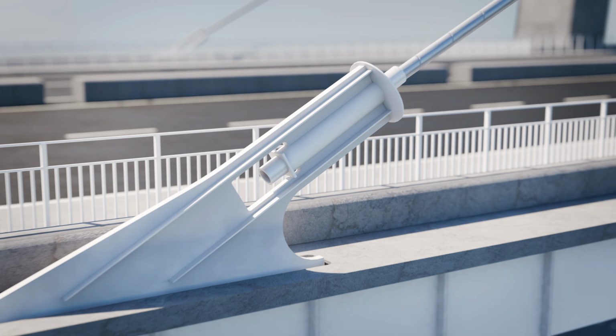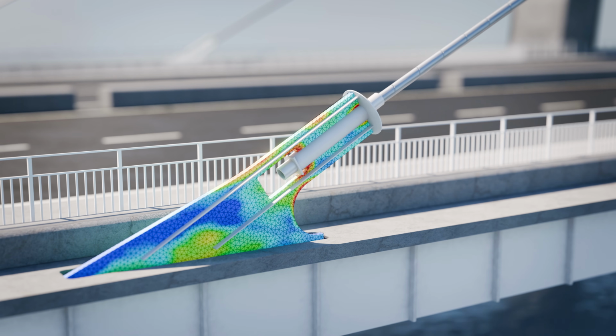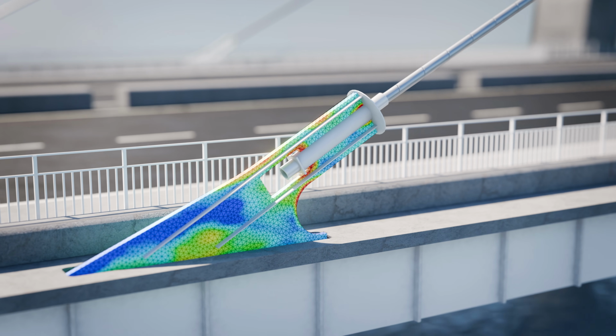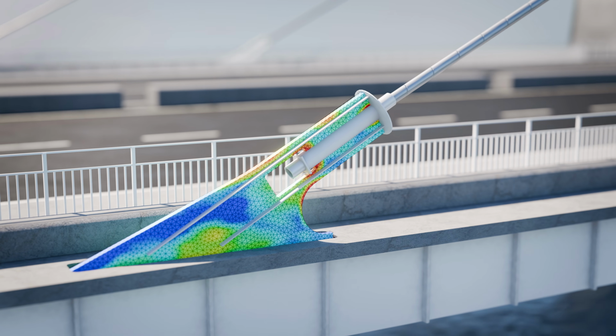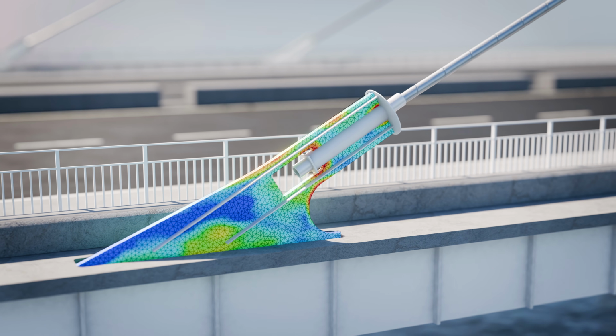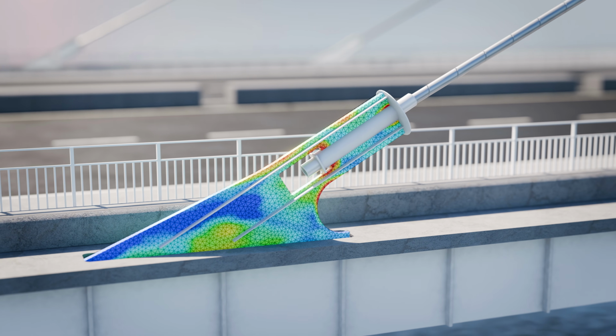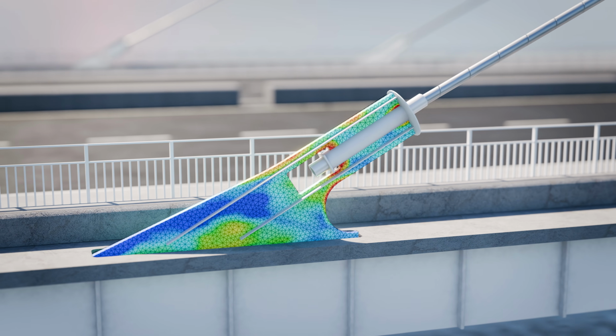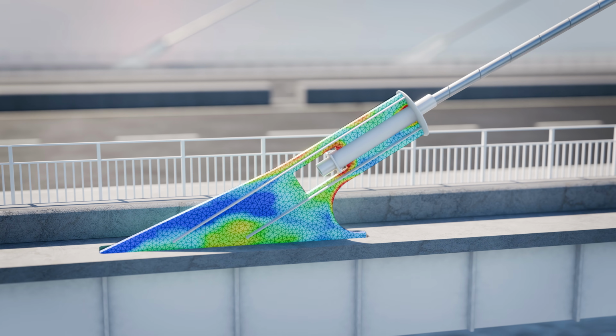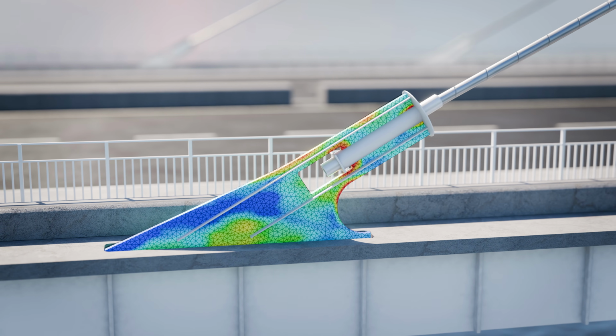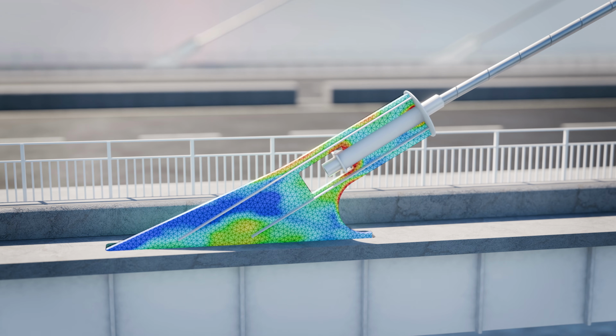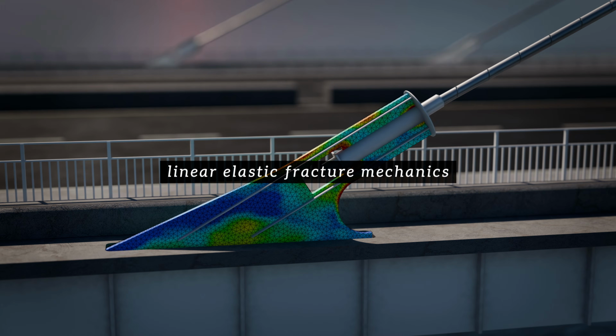Combined with a structural analysis of the bridge, this lets you determine how critical the crack is, how much safety margin remains, and whether the anchorage needs to be monitored, repaired, or replaced. This approach, calculating the stress intensity factor and comparing it with the material fracture toughness, forms the basis of a method called linear elastic fracture mechanics.